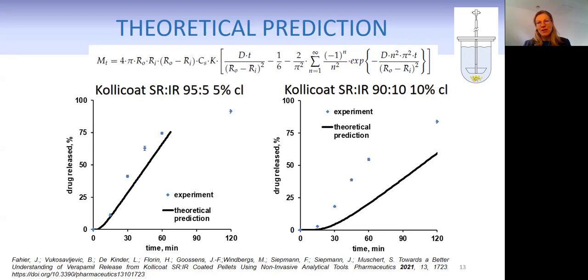So to analyze diffusion controlled release, or to discard the theory of the diffusion controlled release, we applied a mathematical model. The mathematical model assumes that we've got a diffusion controlled drug release method, meaning only the dissolved drug is able to migrate through the intact polymeric film coating. So when we calculate the theoretical diffusion controlled release and compare it to the experimentally obtained data, if theory and experiment fit, we've got a diffusion controlled release. If they don't fit, we've got another drug release mechanism. So let me explain rapidly how the theoretical prediction works.